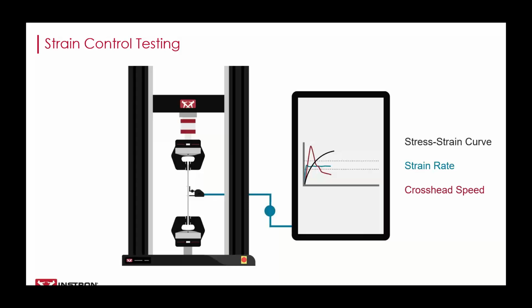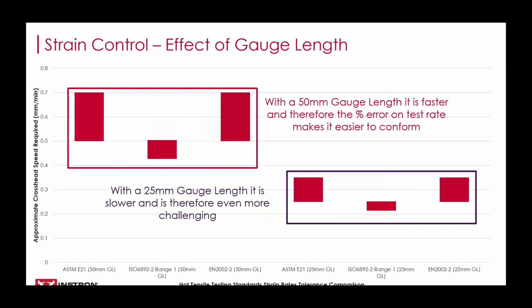We see that here in an illustration of a strain controlled test. The crosshead ramps up at the beginning until the target strain rate is achieved. And then it slows down as the material softens, maintaining that desired strain rate while yield properties are determined. In crosshead speed control tests, the slow speed that is used to achieve the target strain rate at yield will actually be used throughout the beginning of the test. This will lead to the test taking significantly longer. And just to point out again, there's a very narrow window of crosshead speeds that will produce a conforming strain result. And this window shifts depending on the stiffness of the specimen.